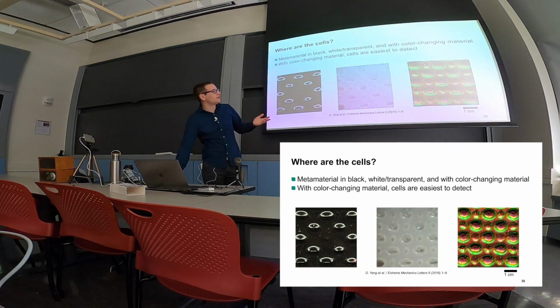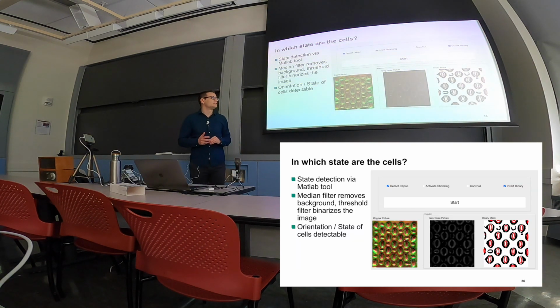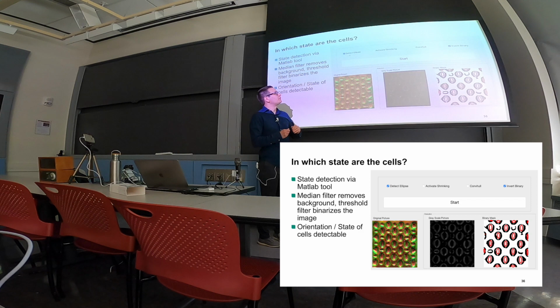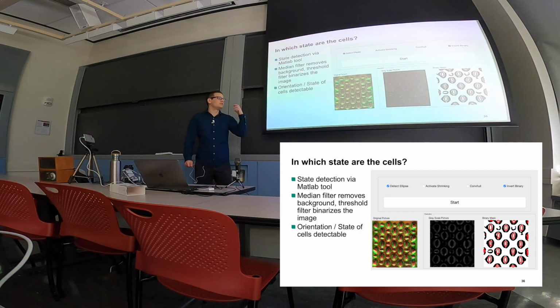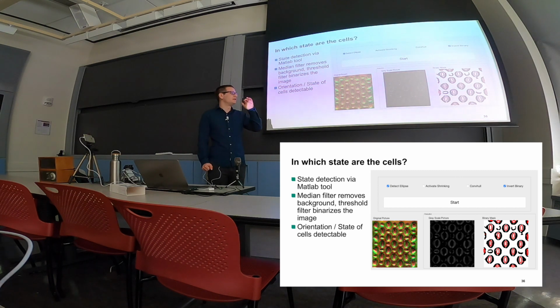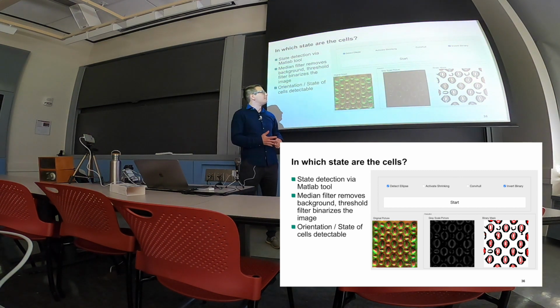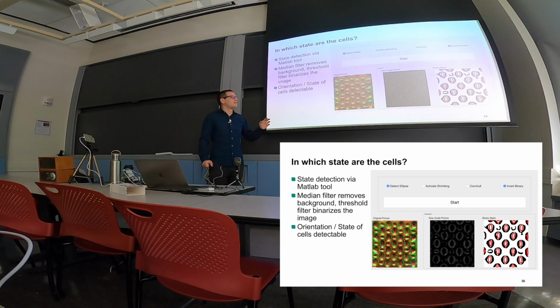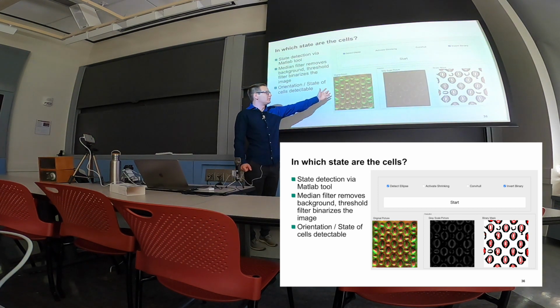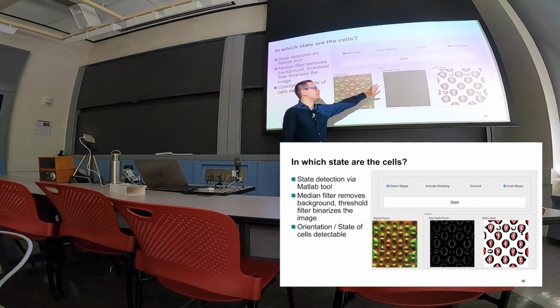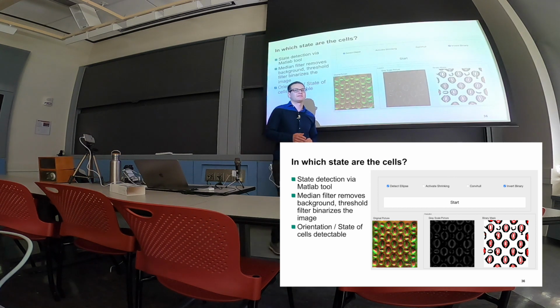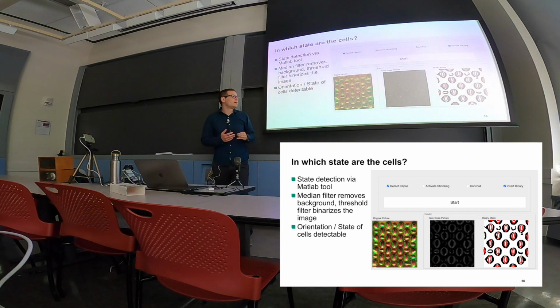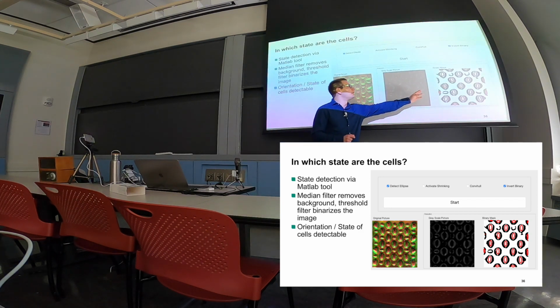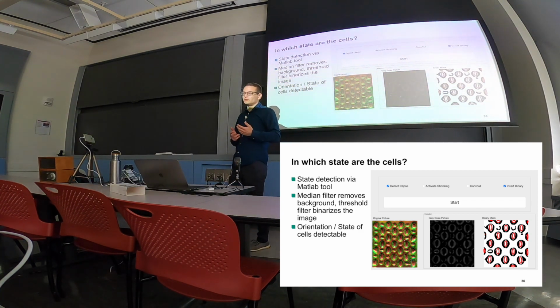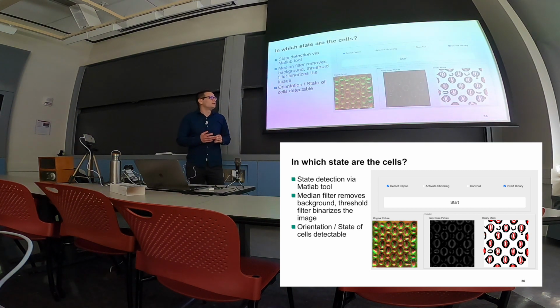And once I was able to show that I can see those cells, then it's not too difficult anymore to sense the state of those cells. So I developed software with a graphical user interface, and then I took an RGB image of the surface of that metamaterial being in one of its stable states. So here standing, so snapped through into a standing rectangular. And then I could just load my RGB image into the graphical user interface that I developed, and then grayscale that image and binarize it, and then with a function that detects ellipses inside of such an image, I could detect where the ellipses are and in which direction those ellipses point. So here, for example, we see the ellipses are standing, so we can say, okay, in this section of the metamaterial, we already know the state of the metamaterial out of just one RGB image.